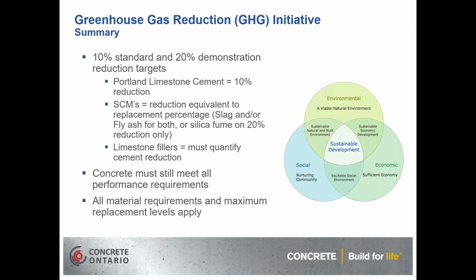So in summary, we have a 10% standard reduction that's required for all MTO works and 20% reduction required for some demonstration projects. The Portland limestone cement is considered to give us a 10% reduction to the greenhouse gas emissions. SCMs, the reduction is equivalent to the replacement percentage for the slag and or fly ash or the silica fume on the 20% reduction demonstrations. And the limestone fillers, we must quantify the cement reduction over our old standard mix design.